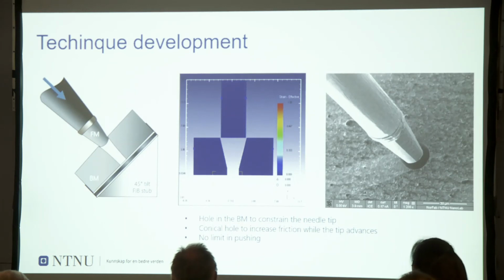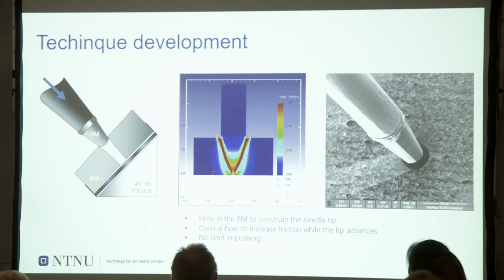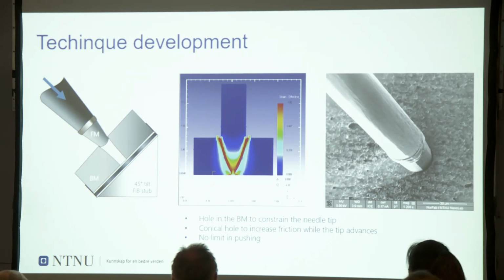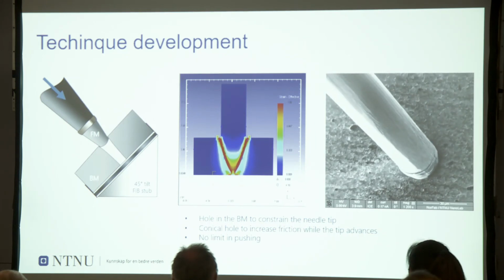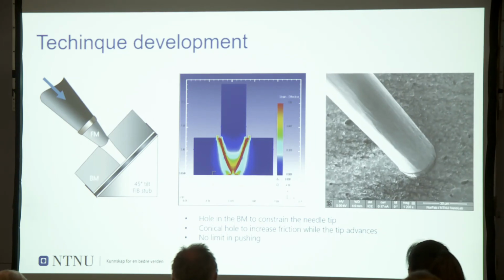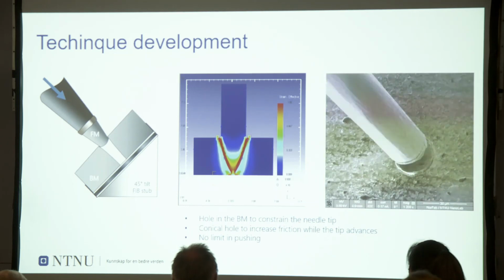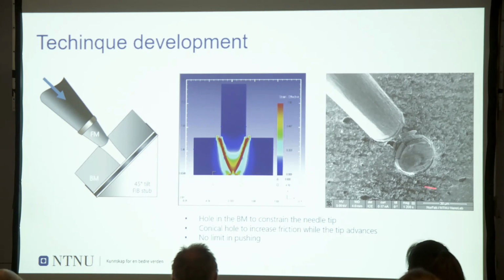So the idea was actually to have this filler material, and this was the base material. We performed some numerical analysis to understand the capacity of this and how to better design the inclination of the hole. And after that, finally, we were able to obtain the first in situ welded component. It's nice because the needle breaks here at the interface, and that part remains welded in the base material.